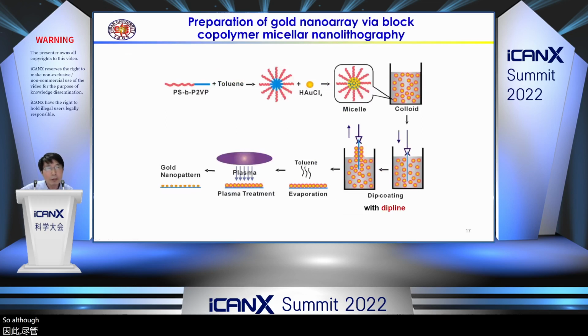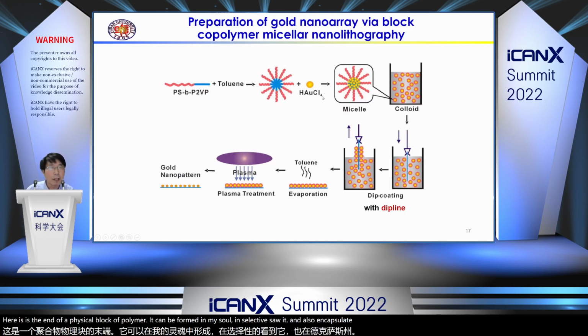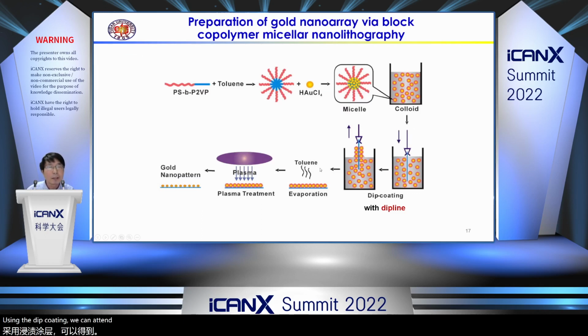So how to generate the pattern? We employed the block polymer micelle lithography. Here is the amphiphilic block polymer. It can form the micelle in selective solvent and also encapsulate gold acid into the core. Using dip coating, we can obtain the pattern of micelles, and then we use plasma treatment. The plasma treatment can remove the polymer template, and meanwhile reduce the gold acid to gold. So in this way, we can generate the gold nanoarray.